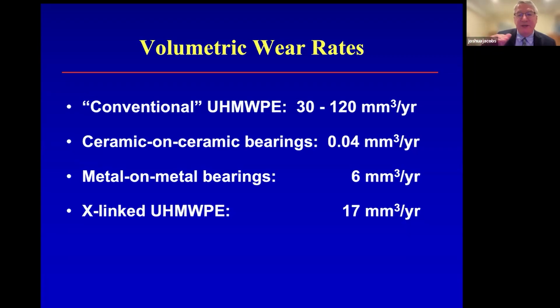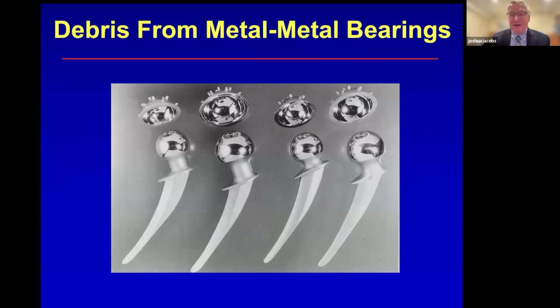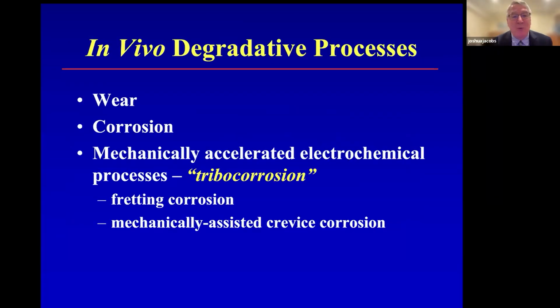And you can see that depending on the technology you're using, there would be dramatic reductions in the amount of volumetric wear. For ceramic on ceramic, a factor of four orders of magnitude, or maybe 1 order of magnitude for polyethylene. So these are the competing technologies at the time. We thought that by reducing volumetric wear rates, we'd solve the problem. Well, it turns out it didn't work out for metal on metal. And why is that? I would posit to you that the reason has to do with the biology of the debris that's generated from the metal on metal wear.